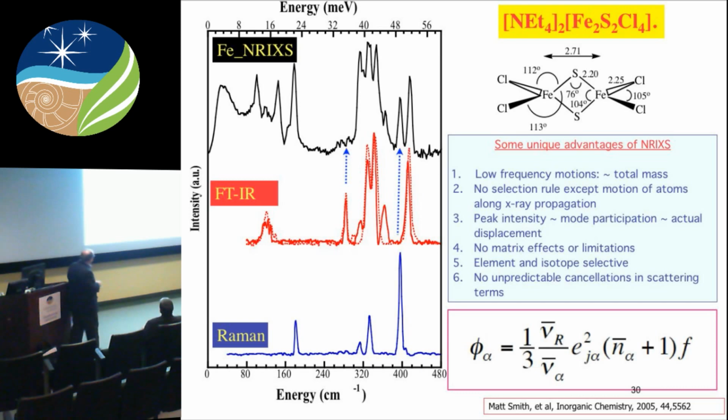Yes? I have another question. So if you do high pressure experiments, often you have preferred orientation, or non-hydrostaticity. That's a very good point. Yes, in fact, we made those mistakes early on, but later on we learned gas loading, and so you pay attention to hydrostatic conditions, all right? And indeed, if you have texture, your spectrum will be heavily influenced by texture. I have another question. Yes.